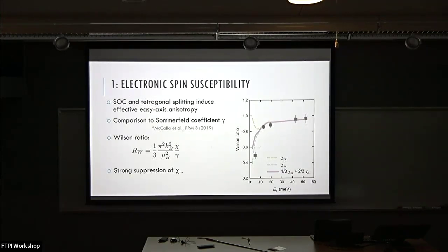Yeah. So is the dashed line a calculation? Yes. Oh, okay. All 3 of these are calculations. And this is, so it's a multi-domain sample. So you're basically seeing 1/3 of one and 2/3 of the other. But yeah, these two are just the two susceptibilities. And the nice thing here is that, again, there's one adjustable parameter to fit the data to the line, and that's the hyperfine coupling. The hyperfine coupling for titanium is known, and the coupling you need to get this is roughly aligned with this. It's not quite the same, but it's pretty close. So this gives us reason to believe that this whole story is essentially correct.